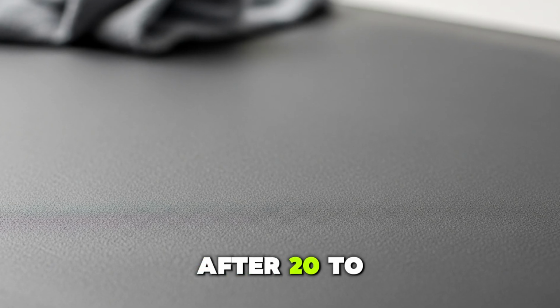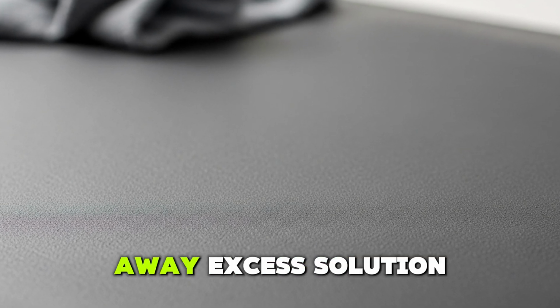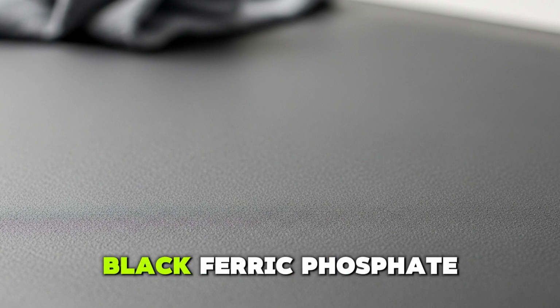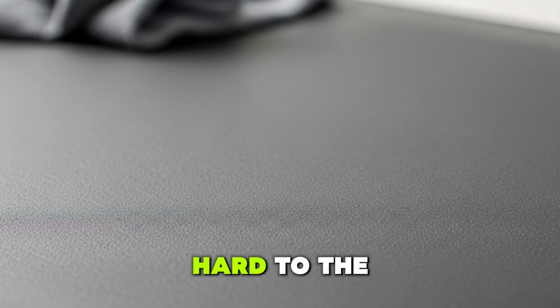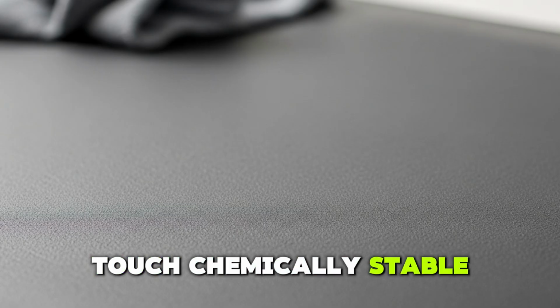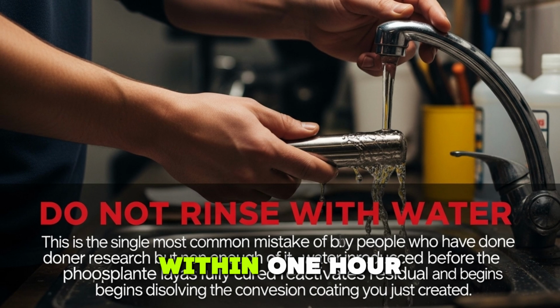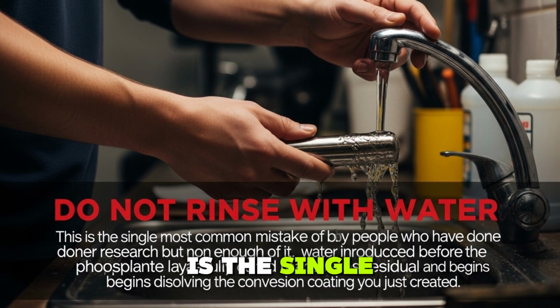If the environment is above 90 degrees Fahrenheit, work in shade and reapply if the surface dries before the reaction window closes. After 20 to 30 minutes, wipe away excess solution with a clean rag. What remains is a matte grey-black ferric phosphate layer, hard to the touch, chemically stable, and ready for your next step within 1 hour. Do not rinse with water. This is the single most common mistake made by people who have done their research but not quite enough of it.